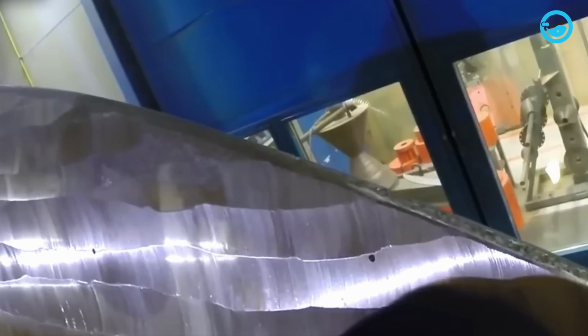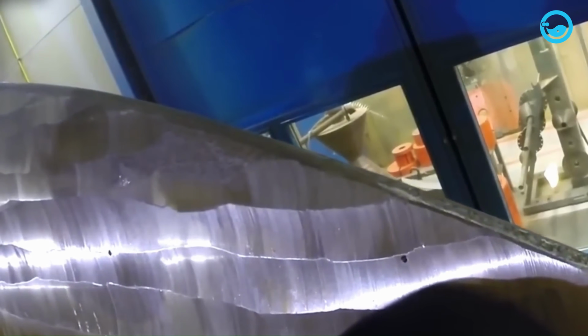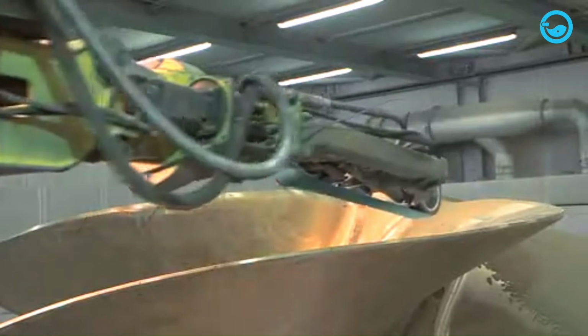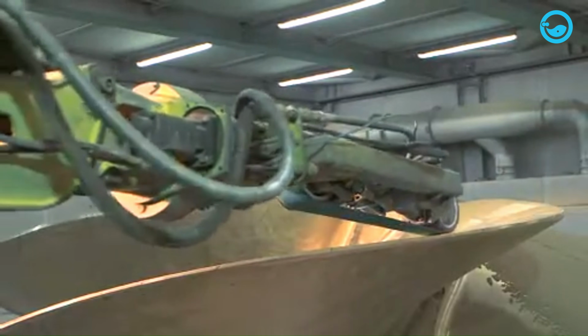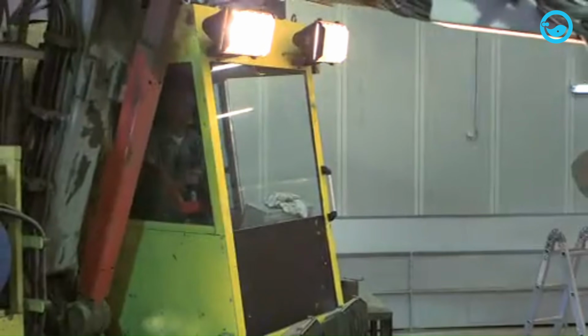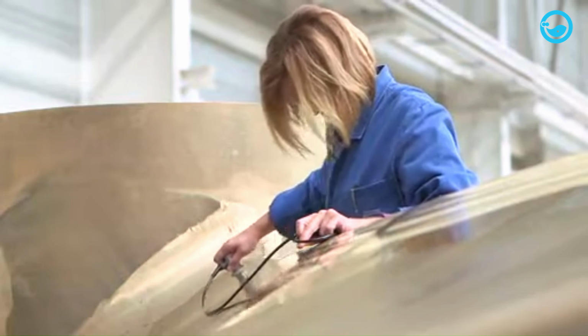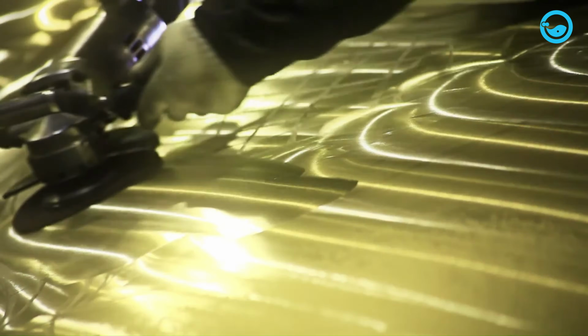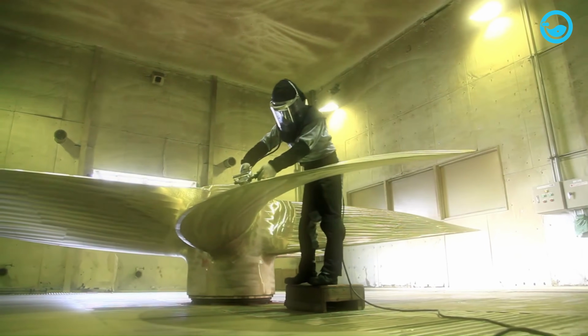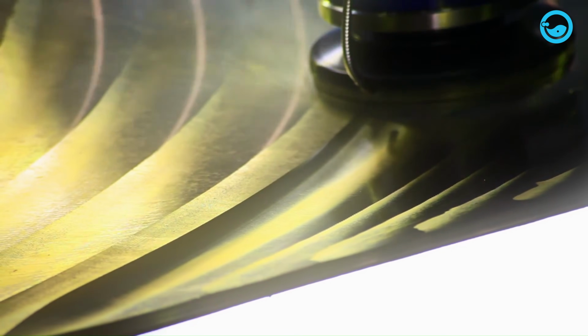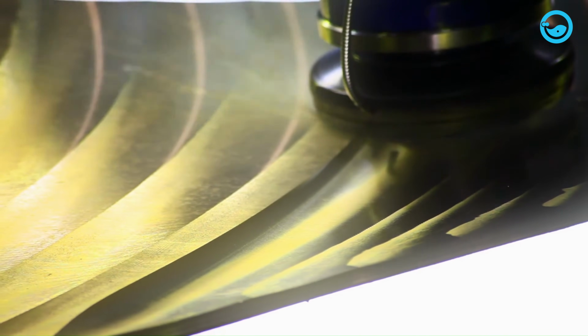Cutting and grinding expose the true surface, which is when obvious imperfections become easier to see. A small surface mark may be removable. A deep shrinkage cavity, crack, blowhole, or non-metallic inclusion is a different problem. Classification rules restrict how defects may be removed and where welding repairs are allowed. The most highly stressed parts near the blade root receive the strictest treatment because a repair there will face repeated loading every time the propeller turns.